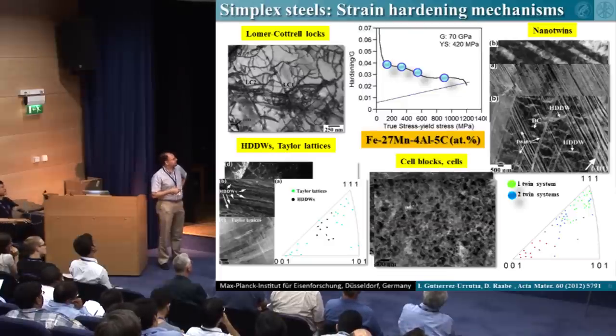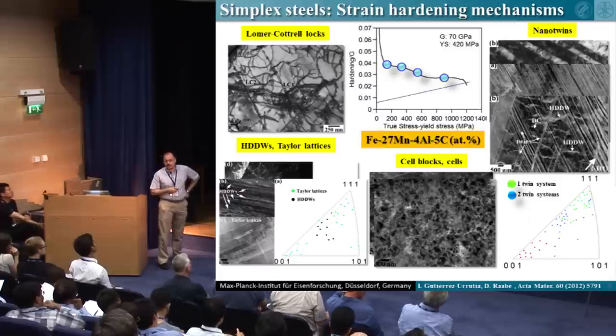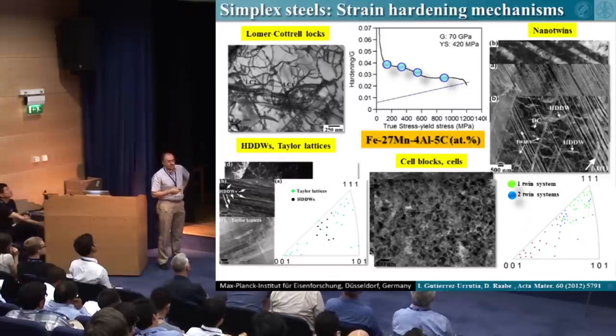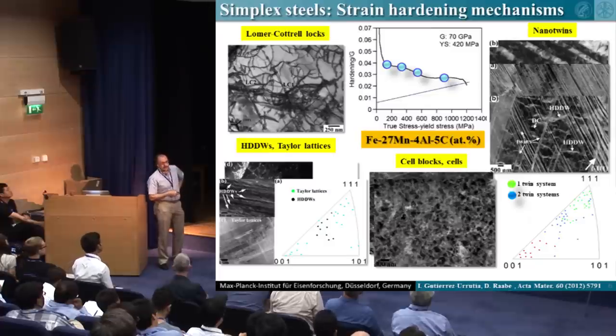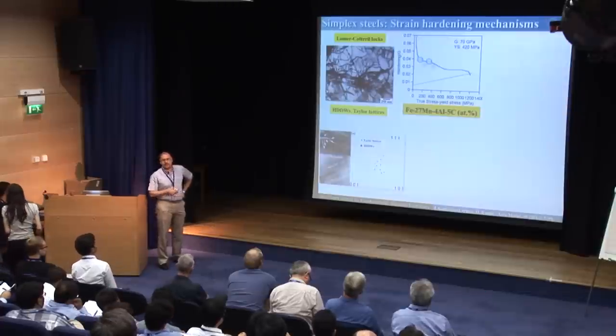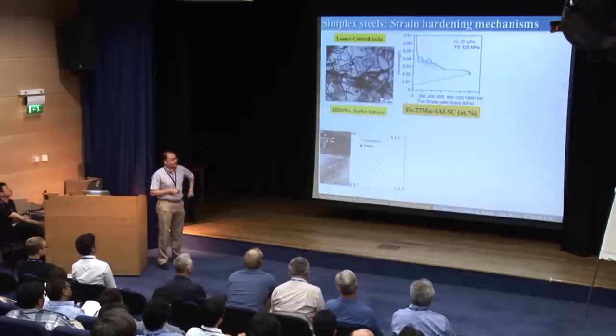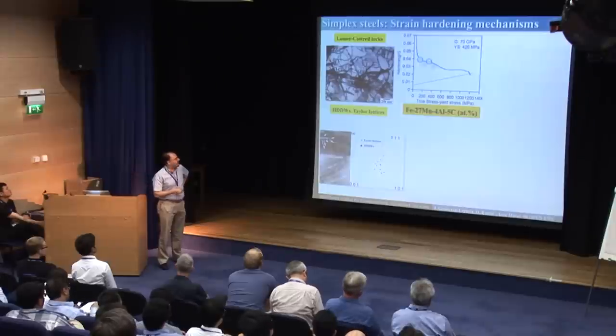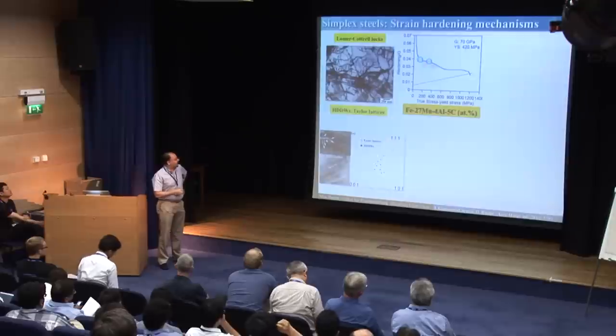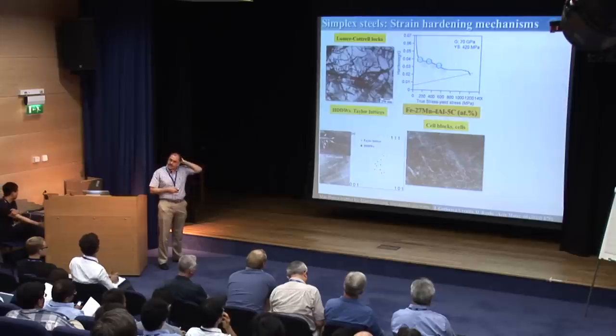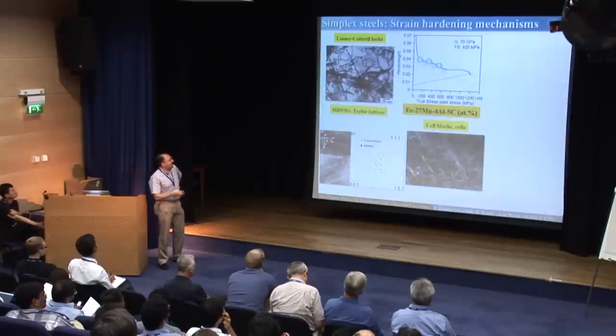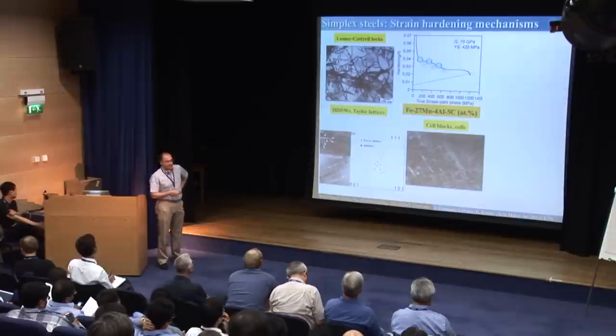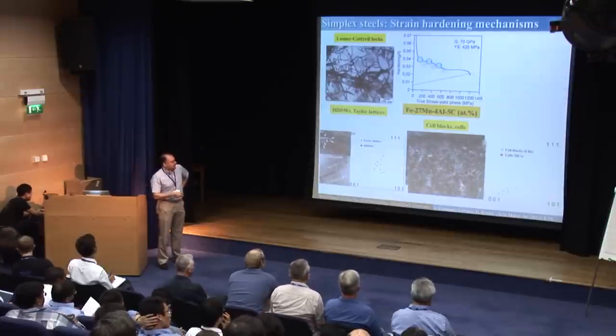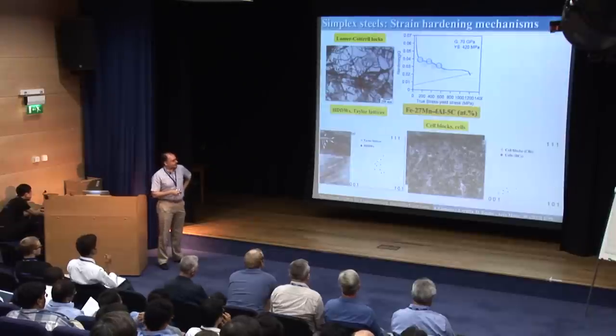Be careful, this is in atomic percent. So in the early stage of deformation, we find classical configurations that can be found in FCC materials, Lomer-Cottrell locks, but interestingly, the formation of highly dense dislocation walls, parallel lines with a characteristic crystallographic orientation. These are dislocation-based structures. Be careful. In order to understand the strain hardening mechanisms, we need to characterize the crystallographic orientation dependence of all these features. And interestingly, this dislocation structure evolves into a more wavy type of dislocation structure, which is basically because the frequency of cross slip is increasing. So at higher stress levels, this dislocation structure is replaced by cell blocks, dislocation cells, also containing a characteristic crystallographic orientation dependence. This is IPF, parallel to the tensile axis under a uniaxial tensile stress.